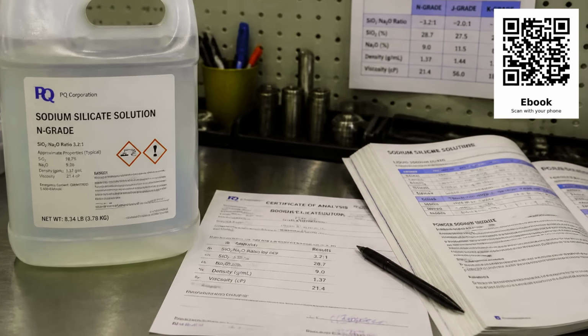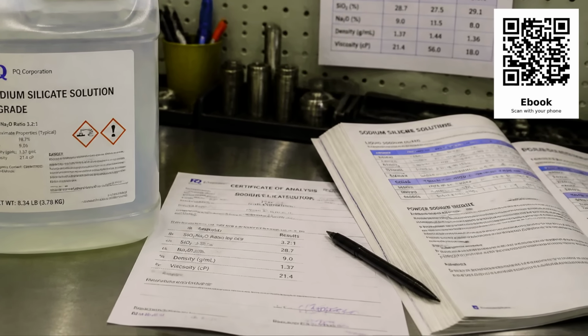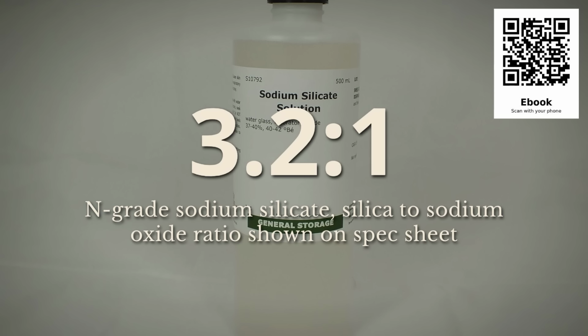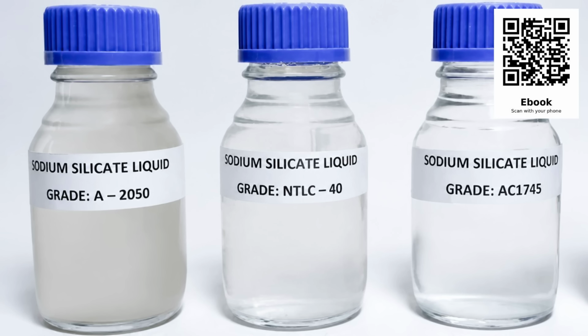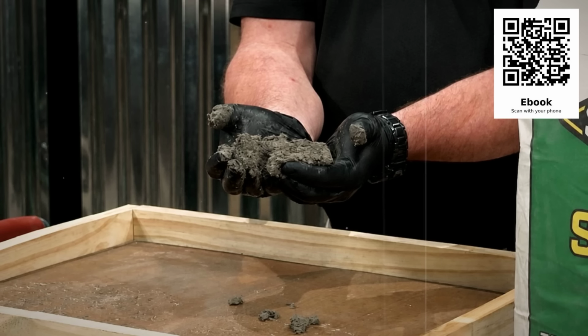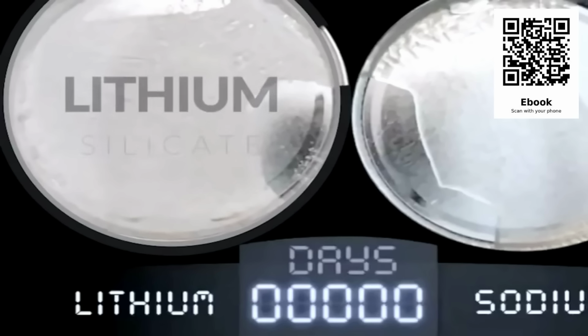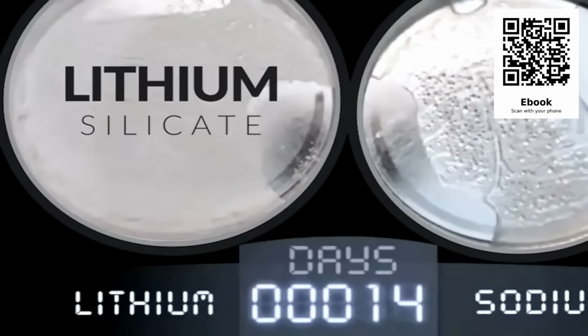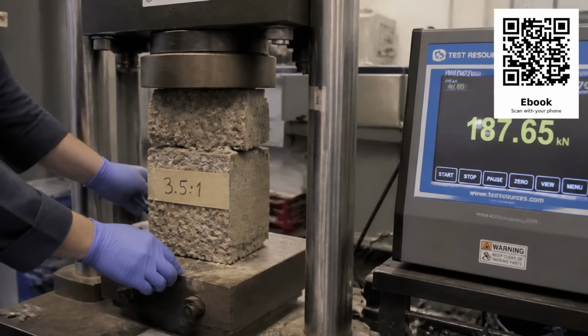The silicate solution itself comes in different grades. The most common is sodium silicate with a weight ratio of silica to sodium oxide of around 3.2 to 1. This is sometimes labeled as N-grade or type N silicate. It is what you want for most construction applications. Lower ratios, around 2 to 1, are more alkaline and cure faster but are weaker. Higher ratios, around 3.5 to 1, are stronger but harder to keep in solution and more sensitive to cure conditions.